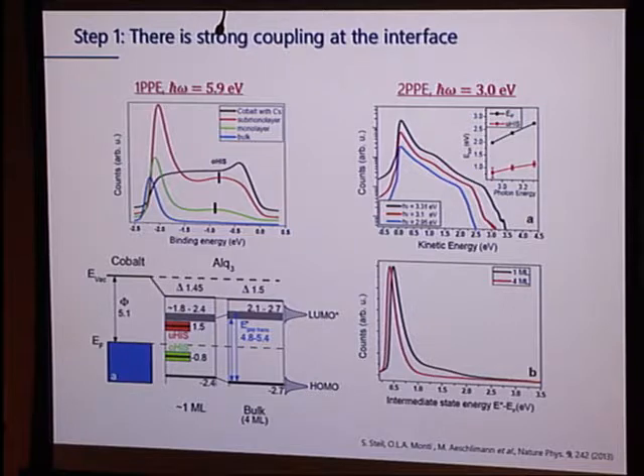This is a hallmark of interaction between the molecule and the surface. Right? They only exist in that first monolayer. They go away after that. We know that through that limited probing depth of the photoemission experiment. And you can see them in here. You can see them also by doing two-photon photoemission. And one does a lot of work to convince oneself that that's true. You scan your photon energy over large ranges, and you prepare these interfaces in many different ways, and this is indeed what comes out. So key point, the first step is to see that there is interaction.